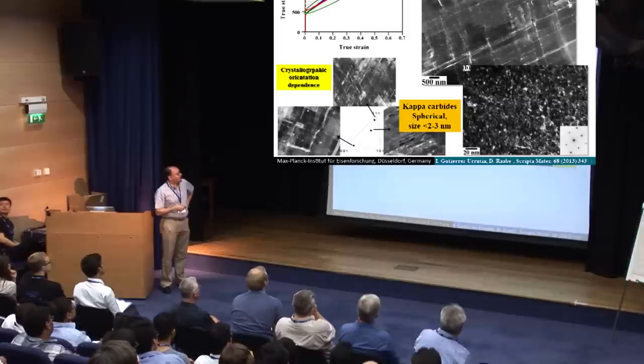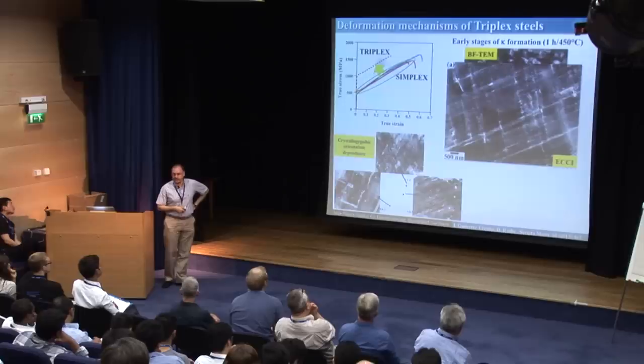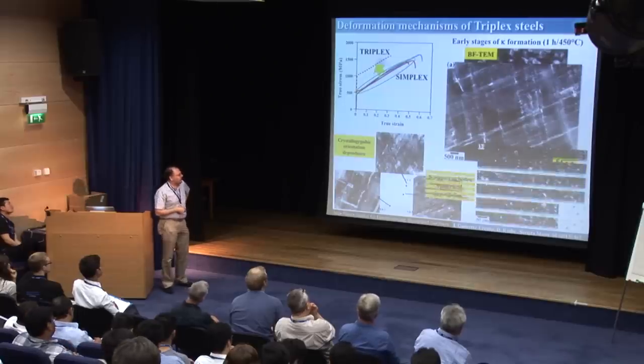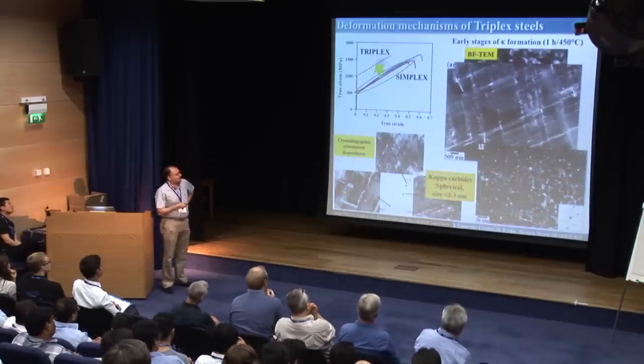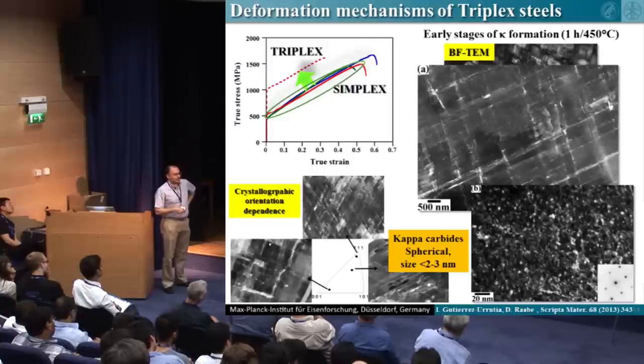We have mainly formation of microbands. So basically, the message here is the addition of aluminum is changing the development of these dislocation structures. Also analyzing the crystallographic orientation dependence of all these patterns. And this is annealing time, where kappa carbides are observed, but the distribution is pretty heterogeneous.